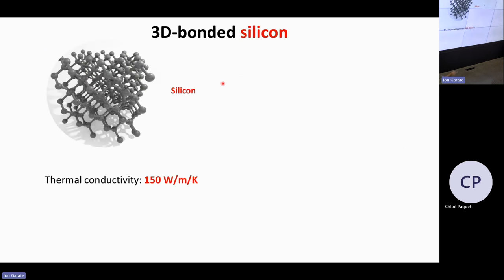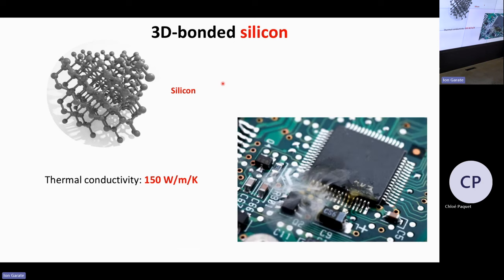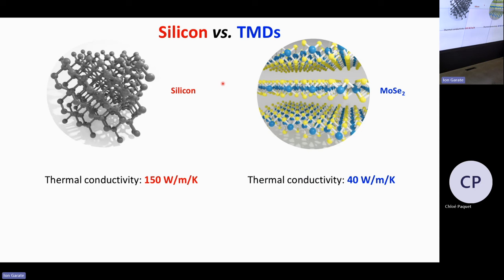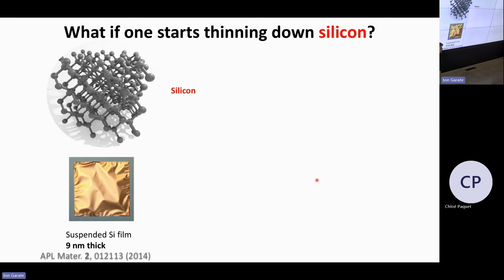So we know silicon has a pretty high thermal conductivity. It's 150 watt per meter Kelvin, not as high as graphene or carbon nanotubes, but it's large enough to avoid this from happening. Now, how does that look for TMDs, transition metal dichalcogenides, so semiconducting layered materials? Well, they're a little bit worse. They're more on the order of tens of watt per meter Kelvin. But that is for bulk material.